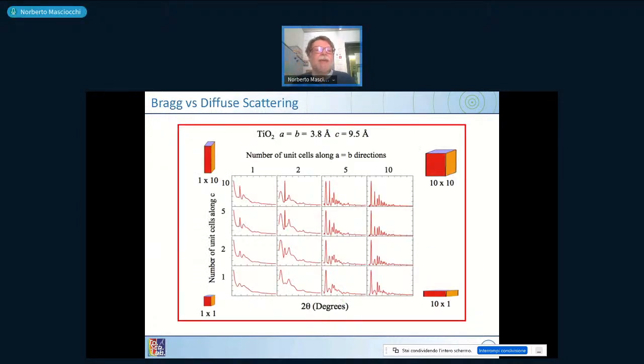Now we just see again what the difference between Bragg scattering and diffuse scattering is. Let's imagine you have a tiny unit cell, a single unit cell of titanium dioxide in the rutile approximation. Then if you have this structure and you compute the scattering factor of a few atoms here, you have something we've seen before, a very poor information system. Now you take this cube and you make it larger. Instead of a 1 by 1 cube, you make it 2 by 2, 5 by 5, and 10 by 10. And so you just move along the diagonal of this plot, and you can see that the bigger the cube, the more definite are the peaks.